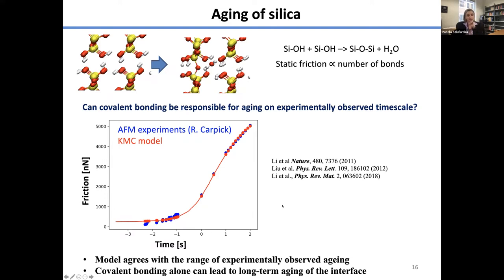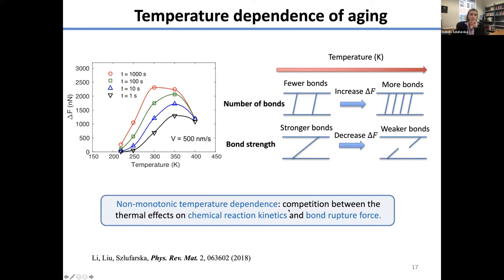This is a single asperity contact. So what we did after that, we took this model and we used it to make new predictions. We said, okay, we know that frictional sliding is going to lead to heating of the interfaces. So we asked, how is the temperature going to affect the contact aging? Is higher temperature more aging? Is lower temperature better? And it turns out that there's an optimum temperature.